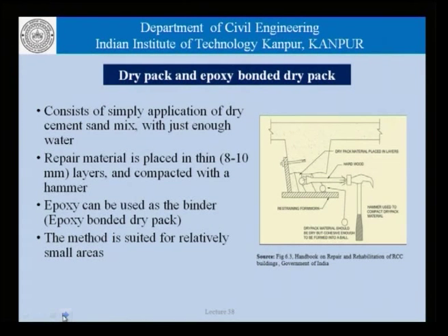Now, what is done here is that we have a portion of the structure here which needs to be repaired. So, what we put in place is a restraining formwork, and we try to pack the repair material in layers. So, we put this layer first, followed by another layer after that, and so on, and this compaction is carried out using a hammer. So, that is the manual method for placing and compacting, and ensuring that this part of concrete which had been removed or which had to be removed on account of some reason is now replaced by another